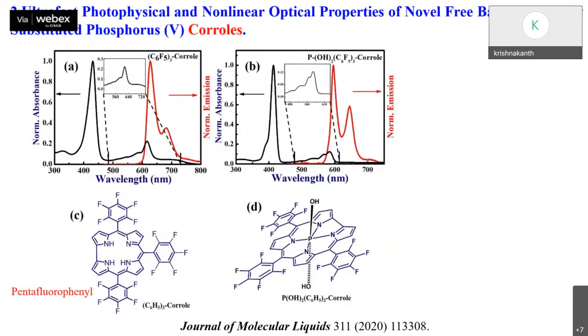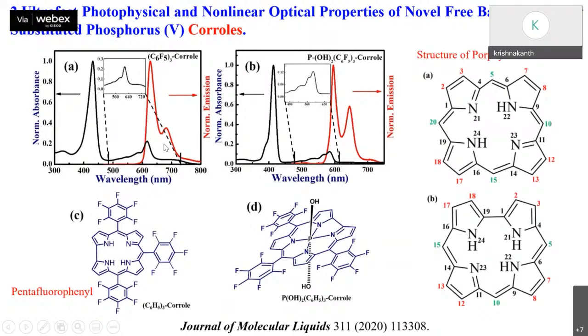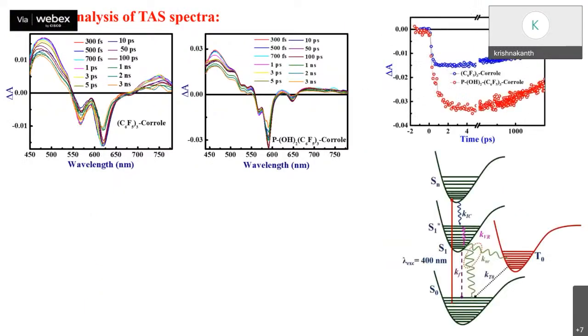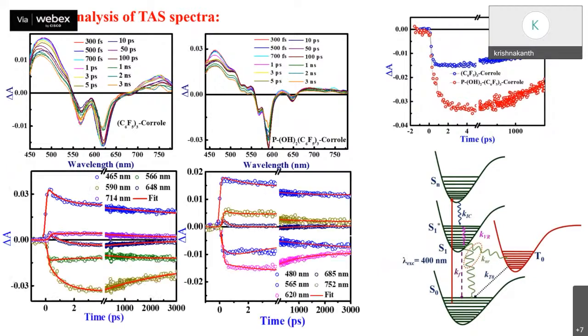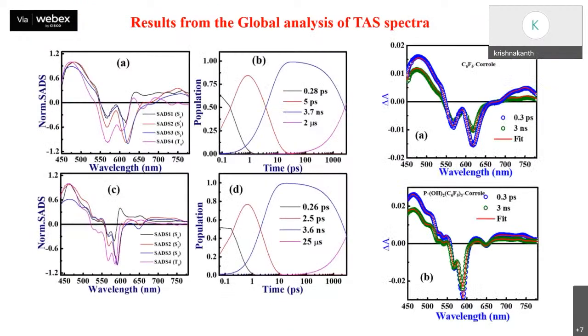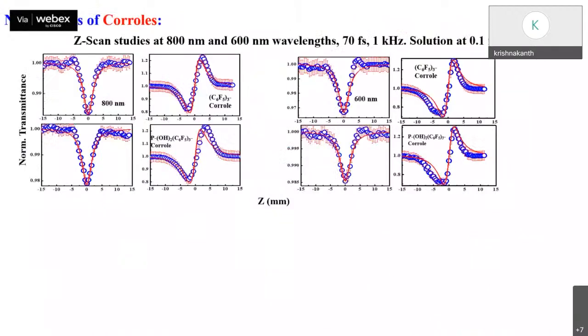Then we have studied similar experiments in a corrole system. These are two corrole molecules: the free base corrole, where there is nothing in the center, and the phosphorus corrole. These are steady state measurements, absorption and emission spectra. From the transient absorption, we can see that phosphorus corrole has strong excited state properties, which has a higher lifetime. This is a global analysis spectrum from the transient absorption of the two corrole systems. And these are the NLO parameters at 800 and 600 nanometer.